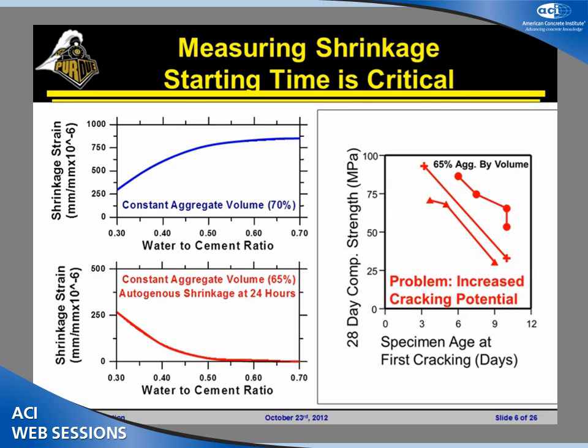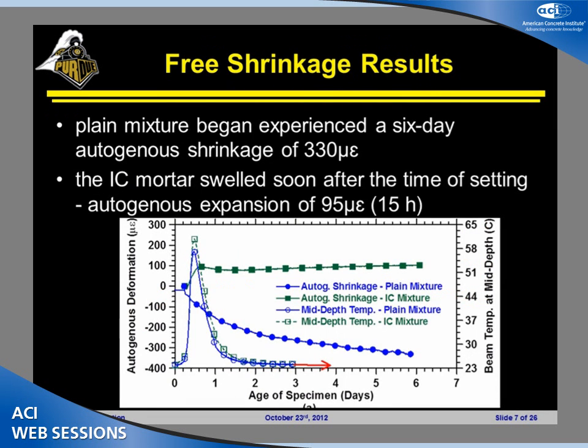So the big thing I want to drive home here is, is high-performance concrete something we shouldn't be striving for? No. But what we need to understand is, as we go to higher strength concretes, modulus goes up, which is not necessarily a good thing. Creep goes down, which is not necessarily a good thing. The shrinkage doesn't necessarily decrease like we think that it may, and the material becomes more brittle. So we have a system that starts to become more susceptible to potential early age cracking.